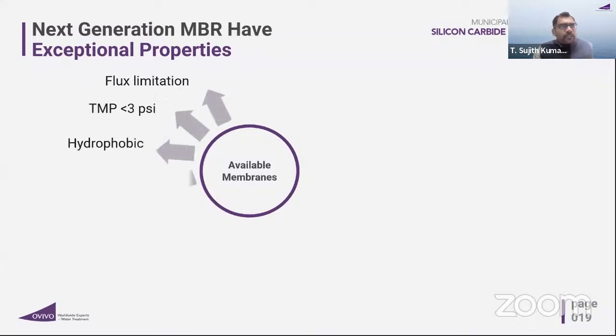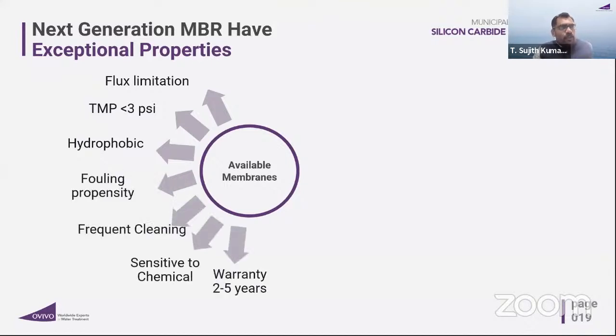Now, what we learned is in conventional polymeric membranes, you have a flux limitation, right? You have a transmembrane pressure limitation. You can't go beyond 3 psi. Membranes are hydrophobic, so there are potential chances of membrane pores getting collapsed during the maintenance activities. Fouling propensity is very high. Frequent cleaning happens, right? Once in 45 days, you need to do the cleaning. And it's sensitive to the chemical because you can't go beyond 3 to 11 pH. And the warranty you get is 2 to 5 years, right?